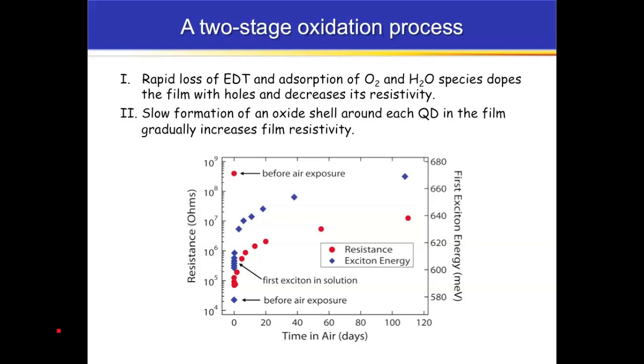That's stage one, and then stage two is a much longer-term buildup of an oxide shell around all the dots that leads to a slow increase in the resistance of the film. At the same time, we can monitor resistance. We can also look at the band gap, which is just a proxy here called the first exciton energy. And we see that the band gap continually marches upward in energy.